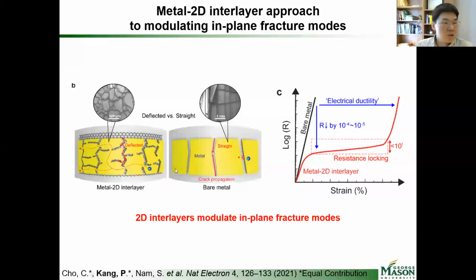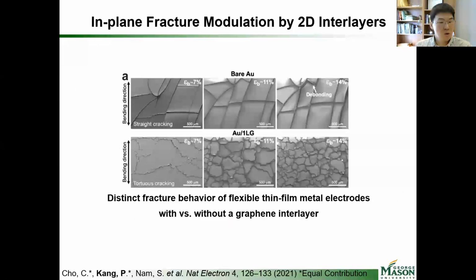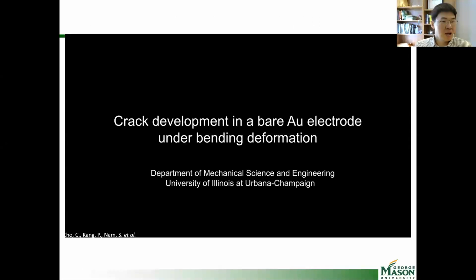You can see as we add the graphene layer on the bottom of the metallic film on the flexible substrate, we can modulate the fracture modes. And as we add this graphene, it turns out that we can modulate the fracture mode, and we can extend and enhance the conductivity of the material. So as opposed to the bare metals, as we add just one thin sheet of the atomically thin material, graphene, under the bottom of these metallic films, we can enhance the conductivity and the mechanical robustness of the material.